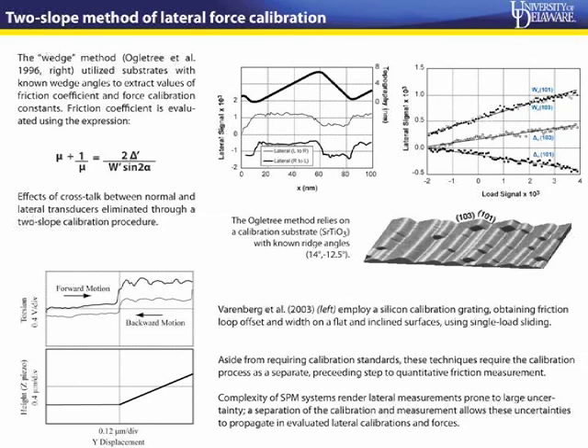You'll notice that the W's overlap because your friction shouldn't change even if you change angles. Now, the two equations that we saw in the previous slide, if you eliminate Cx, Cy, you essentially end up with this quadratic equation, which is one of the formulations of the wedge method by Ogletree and others. Since then, other methods have sought to extend the method. So Varenberg in 2003 proposed a similar method, which was applicable to colloidal probes also. This is just two examples of a wide variety of different methods which have been used for AFM tip calibration for lateral force measurements.